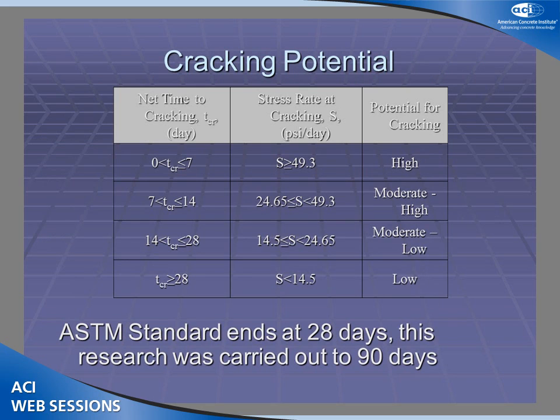The nice thing about this is at this time, BASF out in Beachwood was doing a number of ring tests, and so they helped us with both setting up the test and some literature on how to interpret the results. The problem is a lot of these tests are done on mortars because you get results much more quickly, and you use relatively thin rings. If you want to try to test a 57 stone, you can't really use a thin ring. You have to go to a much larger ring. It means you need to wait longer. The results become a whole lot more confounding, so we tried to make sense out of that. We tried to look at, though, whether our potential for cracking, based on time of cracking and the stress rate of cracking, was high, moderate, or low.